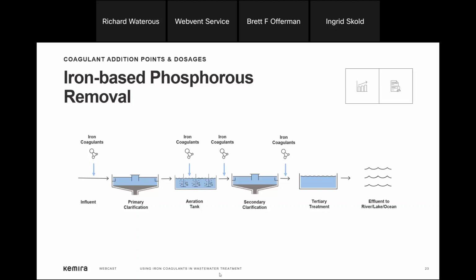At the same time, metal hydroxide forms and creates a gelatinous floc that aids in binding together the metal phosphates and the suspended solids, which includes organically bound particulate phosphate in the wastewater. The contaminants that are present become enmeshed in the hydroxides, causing almost all remaining contaminants to be swept down with the settling hydroxide. This process is known as sweep coagulation. When dosing iron, the presence of soluble phosphorus or phosphates indicates an insufficient coagulant dosage.